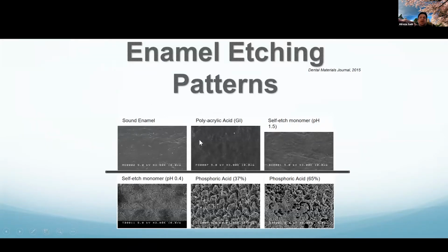Another issue here is the effect of self-etching primers on enamel etching pattern. And the reality is that if you're using a self-etching primer for dentin, for enamel sealant, as say a fissure sealant, you're not really going to get enough etching effect. You're not going to get enough etching effect from a self-etching primer, the 7th generation all-in-one universal bond. So it is a good idea to use a bond, but if you use it without phosphoric acid, then you're not going to get enough etching effect. If you do use phosphoric acid, however, there is a chance of over-etching enamel, right?